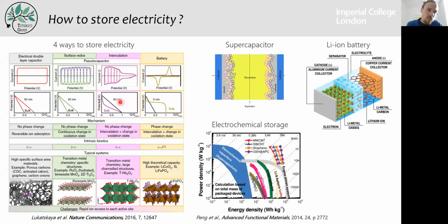And that is basically the role of the pseudocapacitors here that can function either with surface redox or intercalation. And basically, without going too much into detail, what defines supercaps is that you will always have the current here that is proportional to your scan rate. Whereas in a battery, you will have a diffusion limited system where your current is always proportional to the square root of your scan rate.